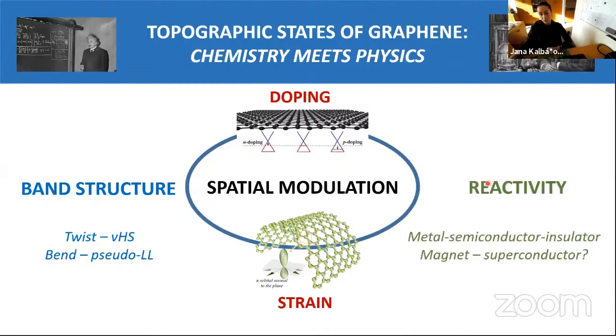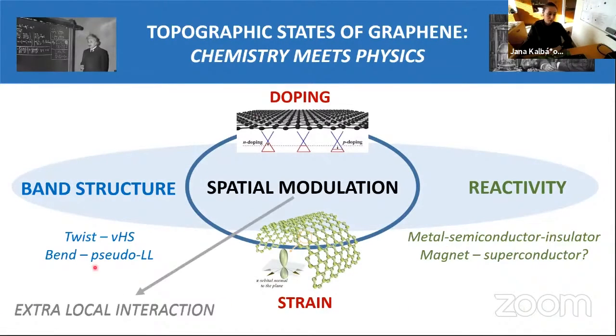Nevertheless, it has also other impact. For example, we can influence chemical reactivity locally. So we can switch the system from the standard state, having an insulator or even a magnet. And finally, there are some other important points. Everything which is here is of course linked together, and there are some other features which I would like to emphasize, and this is specifically at the point of corrugation. If we are using some objects for the corrugation, there could be some local extra interaction. If we are using, for example, fullerenes, there is nothing that special, just there will be some kind of charge transfer effects. Nevertheless, if we are using magnetic objects, there are sources of local time-dependent magnetic fields. So that's something which we can also introduce in the system.